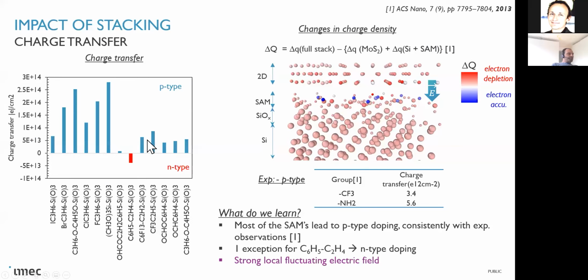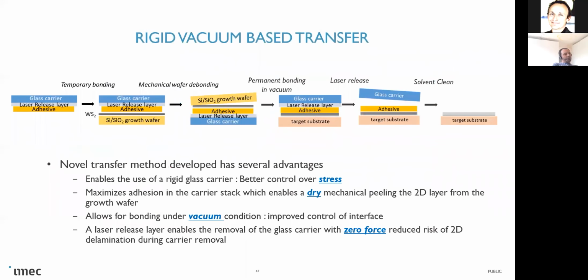Another thing that we see is a charge transfer coming from the SAMs, and basically it's not a uniform charge transfer, so it gives a kind of local charge density variations, which will also affect what is happening there in the 2D material, and it's not an ideal situation. Nevertheless, we are still looking into it to try to find out.